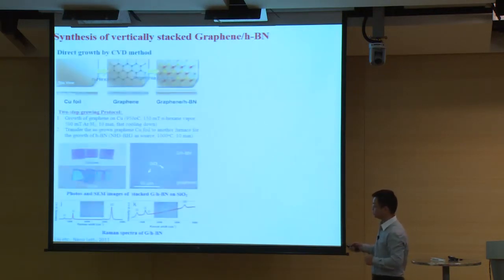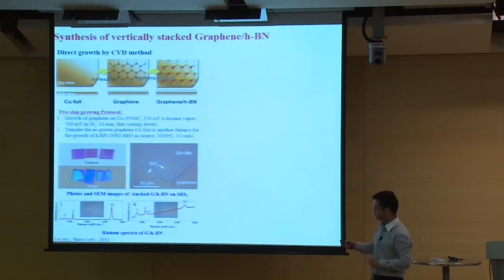Okay. So I just discussed the planar structures. How can we shape engineer the planar boron nitride and graphene? And I just mentioned another way is stacking them together. So we developed two ways to stack them together. The first way, we can grow graphene first, and then we deposit boron nitride on graphene. So like showing here, this graphene only, this boron nitride on graphene.